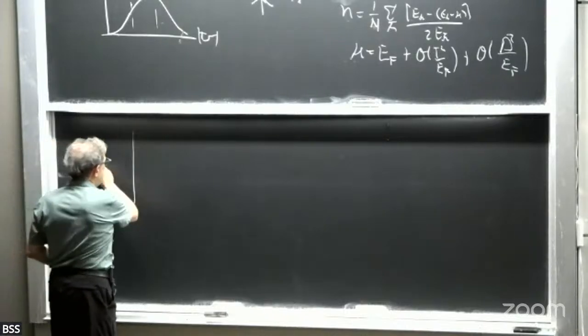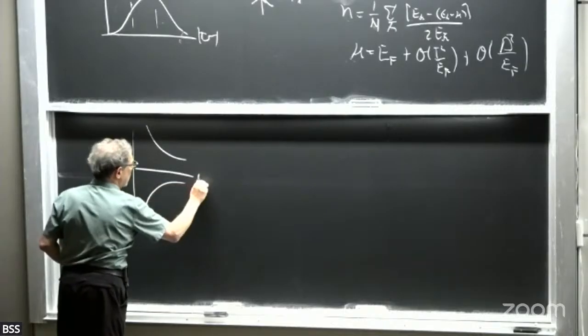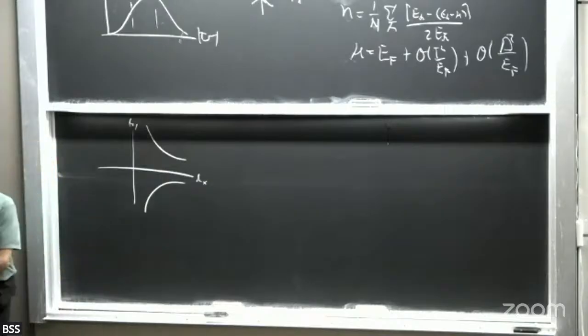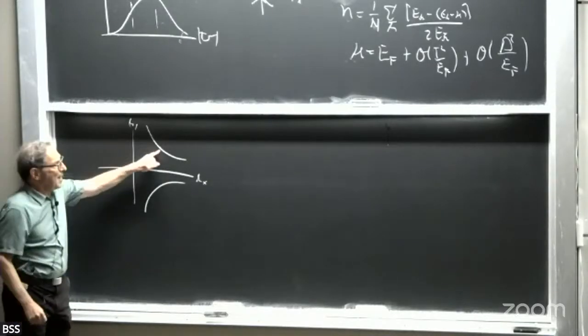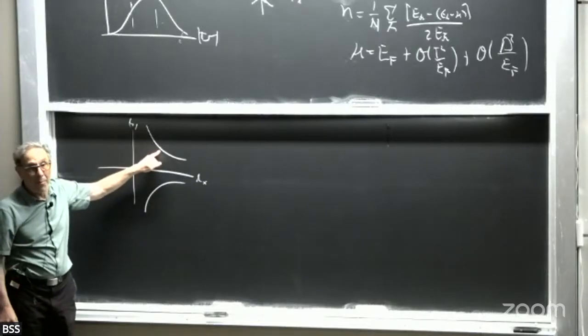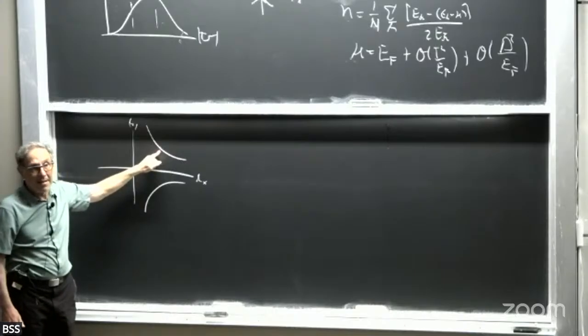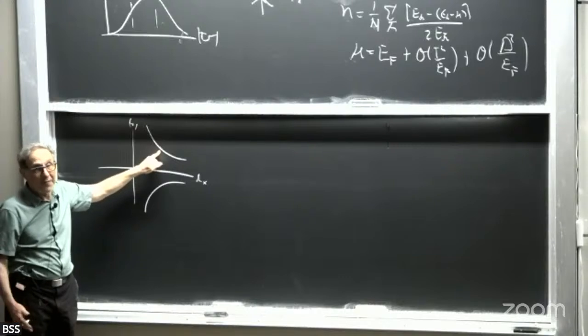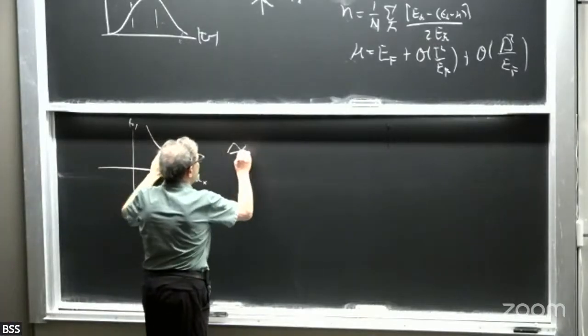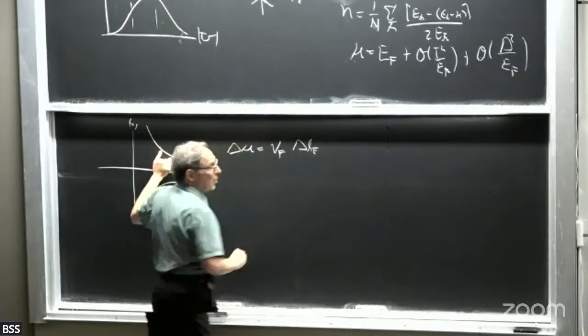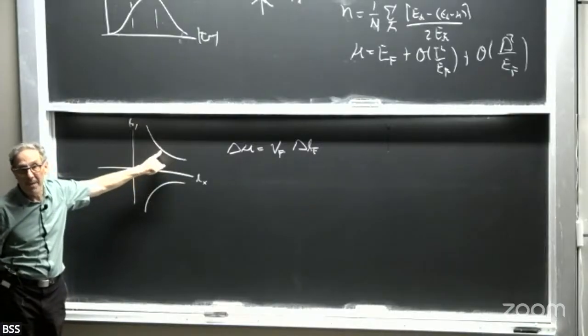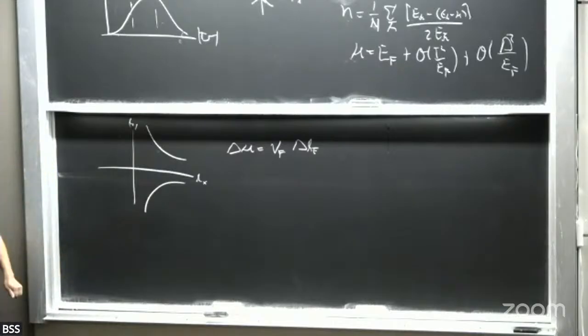So the band structure of the cuprates looks like this. There's a nodal point here. There's a state at the Fermi energy, or more correctly, at the chemical potential. So by looking at this state, both above and below Tc, as a function of doping or temperature or whatever, I can track the position of the Fermi energy here. And in particular, I can look for changes in the chemical potential. Changes in the chemical potential will be the v Fermi times the change in the position of the Fermi momentum. Okay, so that's a gift. This node allows us to track the changes in the chemical potential.